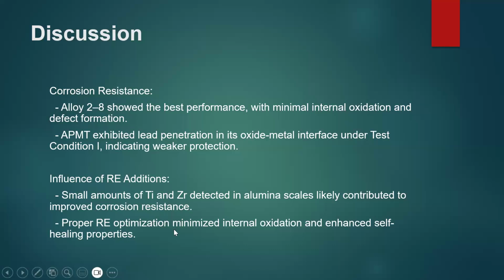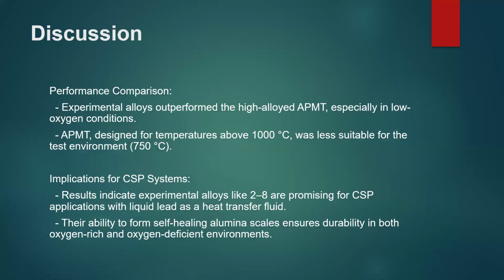Proper RE addition minimizes internal oxidation and enhances self-healing properties. For performance comparison, the experimental alloys outperformed the high alloy APMT, especially in low oxygen conditions.